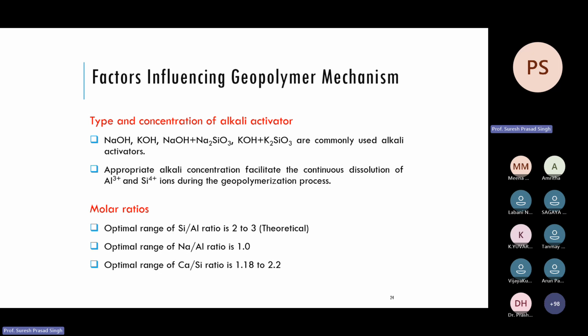Then we have the molar ratio. As I told you, the optimal range of silicon to aluminum ratio is 2 to 3. It is 2 to 3 in the aqueous solution, not in the material. The material may have some silicon to aluminum ratio, but what matters is how much dissolves in the aqueous solution. Whatever is in the aqueous solution takes part in the formation of geopolymer. So after dissolution, the silicon to aluminum ratio in the aqueous solution should be between 2 and 3. The optimal range of sodium to aluminum is 1, and the optimal range of calcium to silicon ratio is 1.18 to 2.2. If these ratios are maintained, we will get a better geopolymer with better strength and durability.